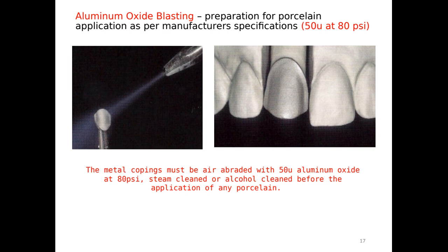So the last step, after we finish reshaping and contouring and fitting the coping, will be to lightly sandblast the coping, and that does two things. First, it removes any impurities that might be embedded in the surface of the alloy, but it also conditions the surface of the alloy to receive porcelain. The metal copings must be air abraded or sandblasted with 50 micron aluminum oxide at 80 psi. I will say that in terms of the size of the aluminum oxide particles in microns, and the pressure, always consult the manufacturer's instructions. And after the sandblasting procedure is done, steam clean it or alcohol clean it before the application of the porcelain.